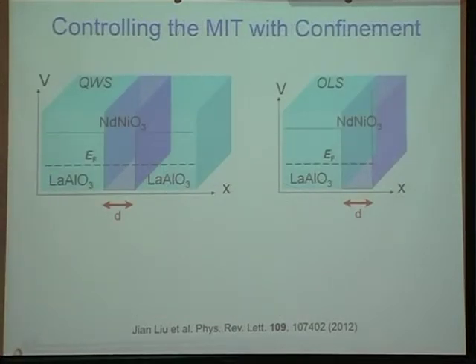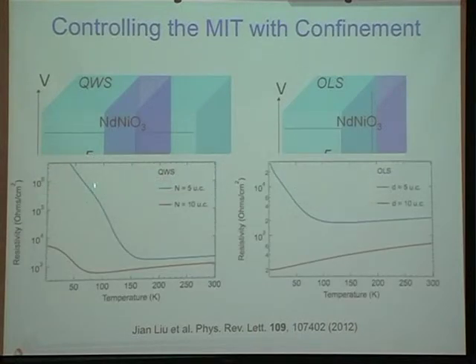So what we did then was we made a heterostructure of these materials. So now I'm going to compare two, neodymium nickelate that has basically lanthanum aluminate on either side. You can think of this as like a simple quantum well. Or I can have a single layer of this film. And then one can play with the thickness of this layer to basically isolate out what is interface versus stuff going on in the bulk of the layer. And what we found was when the layers are thick, you see like before, it's still metallic. Even here in a quantum well, it's metallic with a very small upturn. But when the layers are thin, I can completely bring back that insulating state.